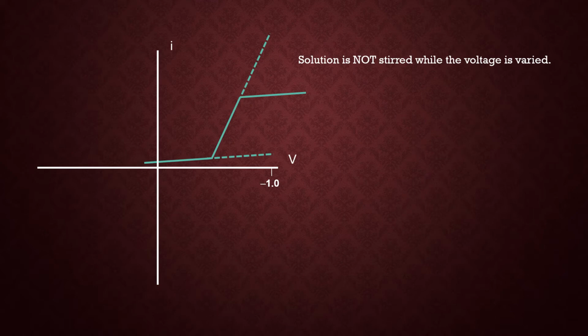Okay. Now, when the solution is not stirred, there's a difference in behavior. So you see the same discontinuity, but it reaches a limiting value indicated by the plateau on the right. So instead of continuing up in that linear fashion, it forms a plateau, and the plateau is roughly parallel to the original conductivity of the ions in solution before the electron transfer took place. This is known as the diffusion limited current. So this means that when the solution is not stirred, you have essentially removed all of the reducible species at the surface of the electrode, and the current is now limited by the diffusion of that same electroactive species from the bulk of the solution.